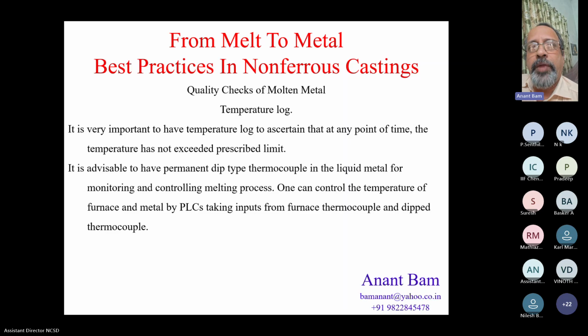When you are refining the material by titanium and boron, the effectiveness of grain refiners vanishes after high temperature, maybe exceeding 780 degrees Celsius. And that change is irreversible. The titanium is visible in the spectrometer, but it fails to refine the grains. So you have to ensure that in the life cycle of casting, that is from solid to melting to holding to treatment to casting again, it has not crossed 780 degrees Celsius at any point of time. That is why it is important to have a temperature log or to have a permanent dip type thermocouple connected to PLC, having a direct shut off control on the furnace.